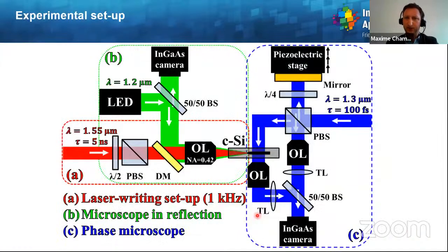So in order to investigate the influence of nanosecond pulse irradiation inside silicon, we have developed another setup relying on 1.55 micron wavelength pulses at 5 nanosecond duration. Then, same as previously, we adjust the pulse energy with a half-wave plate and a polarizer, and we use the same microscope for positioning the geometrical focus with respect to the sample.